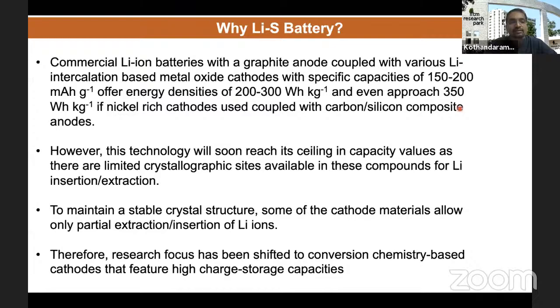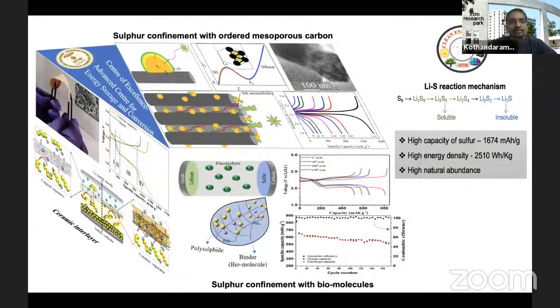So therefore, research is now focusing on shifting to a conversion-based chemistry instead of an insertion-reinsertion-based chemistry. In that, lithium sulfur is very promising. It's a very promising conversion chemistry, and moreover, sulfur is very abundant. So considering the high capacity of sulfur and the high energy density it offers, together with the natural abundance, we chose this lithium sulfur work. Probably we can extend this to sodium sulfur and other conversion-based chemistries as well.